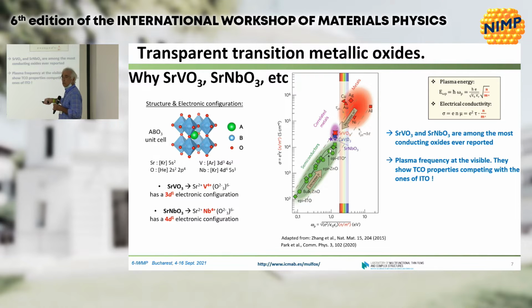Those are the semiconductors I mentioned, indium tin oxide, for instance, and the vanadates, strontium vanadate and calcium vanadate, are in the middle. So they are transparent in the visible, they have a good conductivity, so in principle they are good candidates. And here's what I summarize here. It was proposed that the properties of these materials, these wonderful properties of being conducting and transparent in the visible, with the plasma frequency in the infrared, are related to the correlated nature of the electrons in the system.